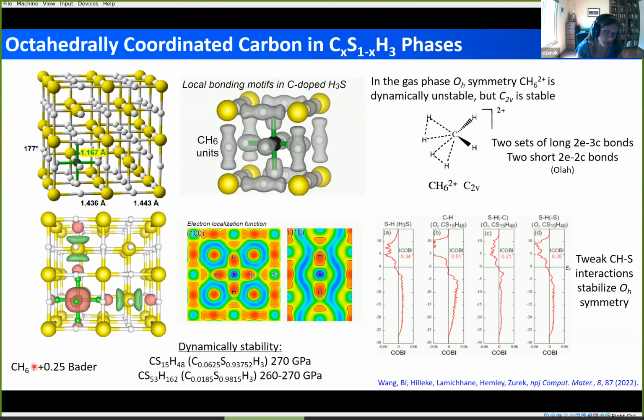And indeed, according to a Bader analysis, you do see that this CH6 does become positively charged, a slight positive charge in the calculations. We do find that there are, however, weak interactions between the hydrogen and the sulfur, not enough to form any kind of covalent bond, but there is some sort of a steric interaction that is keeping this octahedral coordination stable at the very high pressures.